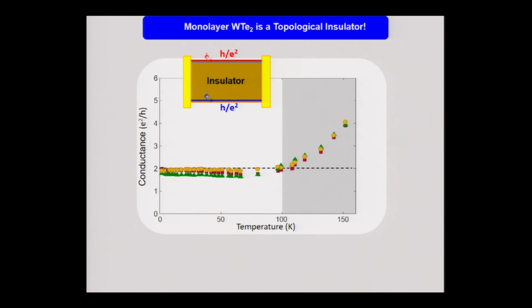Another interesting feature I want to mention is how robust this quantum spin-Hall state is under temperature variation. We increased the temperature up to 100 kelvin, and the state is still robust up to 100 kelvin, as monitored by the conductance. The quantum conductance still stays at 2e squared over h. So this means that compared to previous quantum spin-Hall insulators, where this state can only survive to a few kelvin, we increased the temperature by about two orders of magnitude.